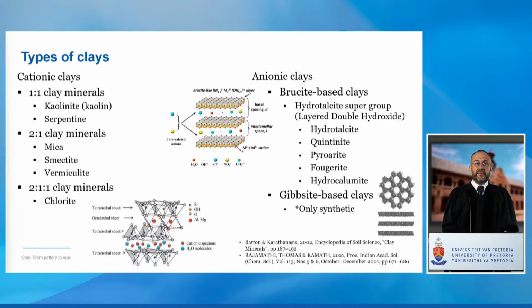Cationic clays are predominantly found in nature and are the most well-known clay minerals. They have different layer arrangements that are used in the names. So you can see we can get 1-to-1 clay ratios, 2-to-1 clay ratios, and 2-to-1-to-1 clay ratios, looking at the structure of the layers versus the interlayer.